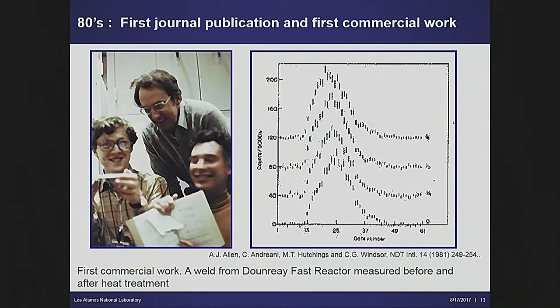The first actual measurements of neutron depth profiling with residual stress happened in the 80s. Those of you that have spent any time at NIST might possibly recognize a very youthful looking Andrew Allen, who works there on their small angle scattering program. This activity, which actually led to a paper in NDT, a non-destructive testing journal, led very quickly to the first commercial work, right? People saw what they could do, and then the Dounreay fast reactor said, well, okay, can you make some measurements of residual stress in a weld for us? And they took the first chunk of money for actually doing these measurements at the Harwell reactor.